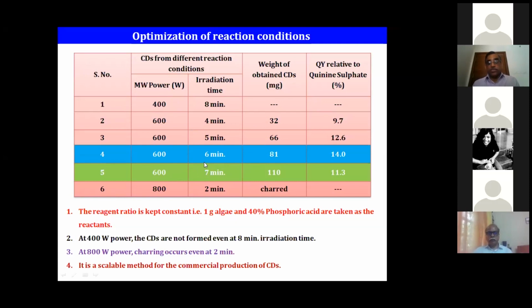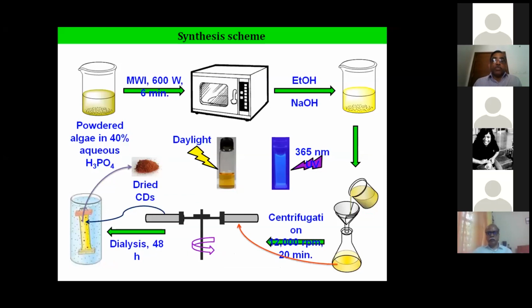When you look at the synthesis using the microwave, you maintain the power, the time of irradiation, and the reagent ratio that we take up. Now, the basic synthesis involved is using microwave power of 600 watts for 6 minutes. In a normal domestic microwave oven itself, one can do this.